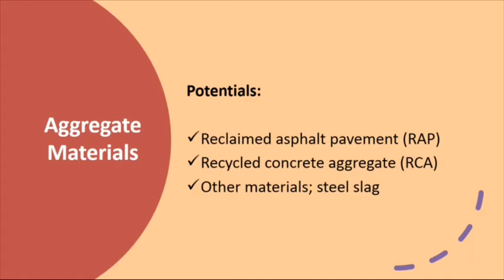RCA is created when concrete is purposely crushed to create aggregate for use in subbase, base or in asphalt or concrete application. RCA often contains previously unhydrated cement that produces increased stiffness in bases or subbases when mixed with water, which creates a material with superior properties compared with the virgin aggregates. When used as a base or subbase, both the coarse and fine RCA are normally used. So other than these two examples of recycled aggregate, there are many more out there, depending on local availability.